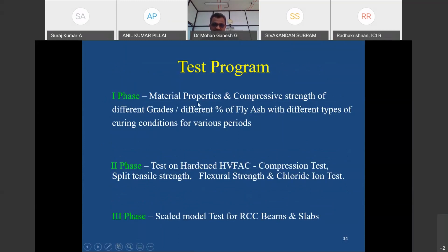In the first phase, we collected the different materials and tested the compressive strength of different grades, different percentages of fly ash, with different types of curing for various periods. In the second phase, we did various hardened tests of mechanical properties like the compression test, split tensile strength, flexural strength, and chloride ion test. In the third phase, we did RCC beams and slabs as scaled models.